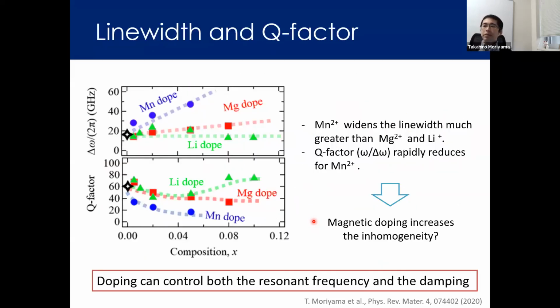So the line width or the Q factor can also be modified by the cation doping. Comparing to the Mg and the lithium, the non-magnetic doping, the manganese doping, which is magnetic doping, seems to increase the line width and decrease the Q factor significantly here, which might be related to the increase of magnetic inhomogeneity due to the doping of this magnetic cation.